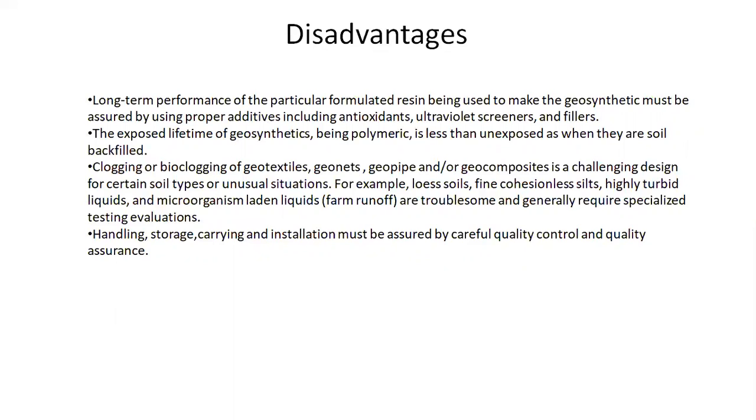Clogging and bioclogging of geotextiles, geonets, geopipes, and geocomposites is a challenging design issue for certain soil types or unusual situations. For example, loessial soil, fine cohesionless silt, highly turbid liquids, and microorganism-laden liquids are troublesome and generally require specialized testing evaluation.